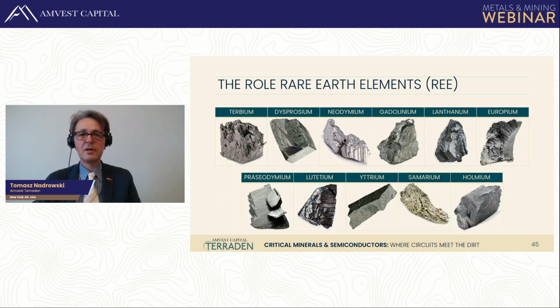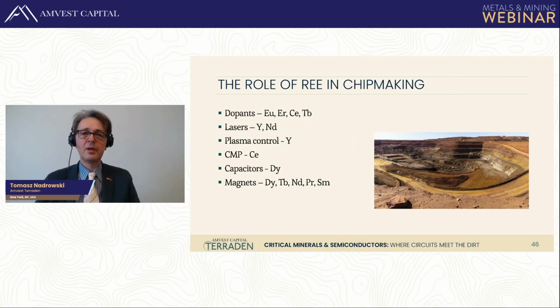But there are other roles that are important for rare earths in production of semiconductors. First and foremost, they function as lasers. I already mentioned the yttrium aluminum garnet laser, and yttrium is a rare earth element, not a lanthanide, but associated geologically. And sometimes that laser is also doped with neodymium, light rare earth, to produce the ultraviolet light in lithography. It's also this laser that's used to bombard that molten tin, as I mentioned before.